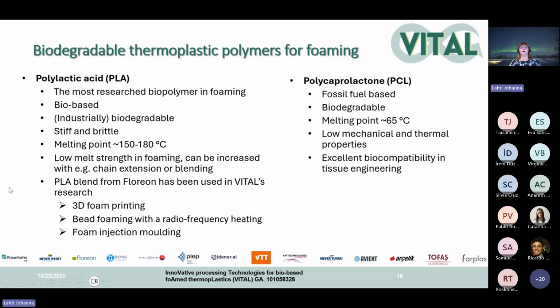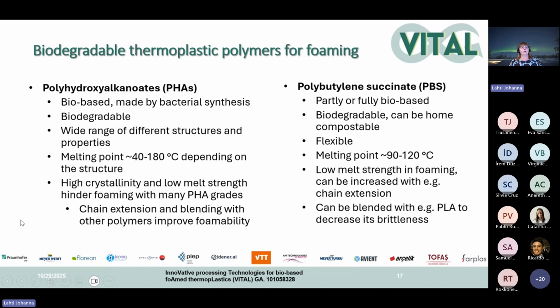Then we have polycaprolactone mentioned here. Maybe I will skip that and go further. Polyhydroxyalkanoates, PHAs, a very interesting group and studied a lot. Not so far that much in foaming, but in other sectors, for example the packaging sector, a very interesting polymer. It is a bio-based, biodegradable polymer, but it can have some challenges in foaming. So it has high crystallinity, it has low melt strength, so that can cause some challenges in the foaming process. So once again, we can use some tricks to affect the foaming with this polymer, for example, chain extension or blending, and this way improve the foamability.